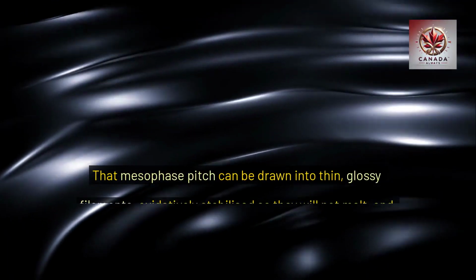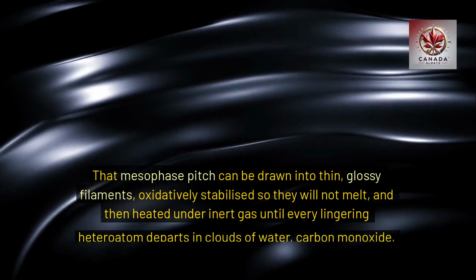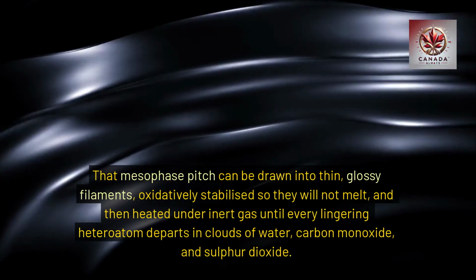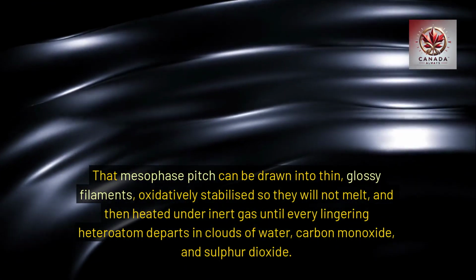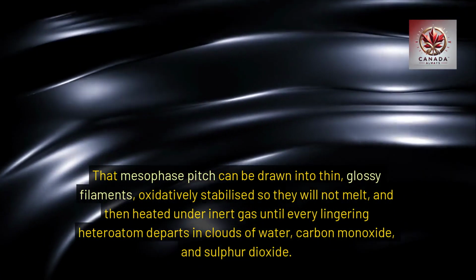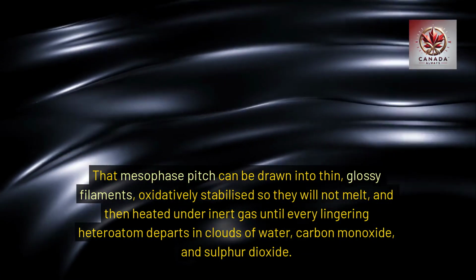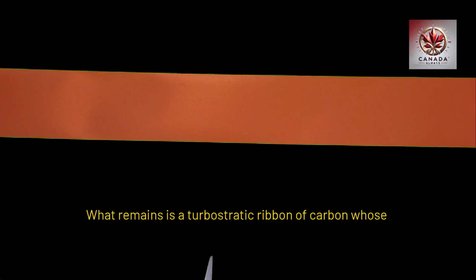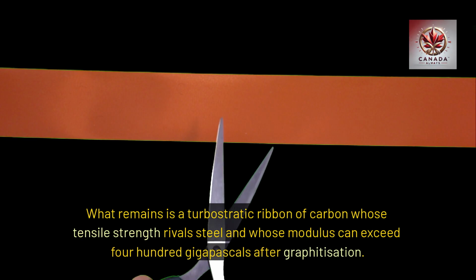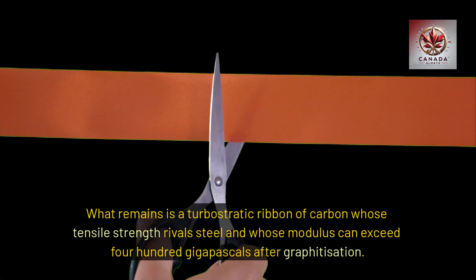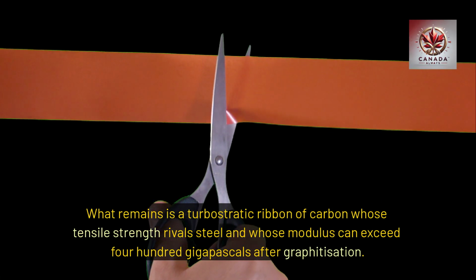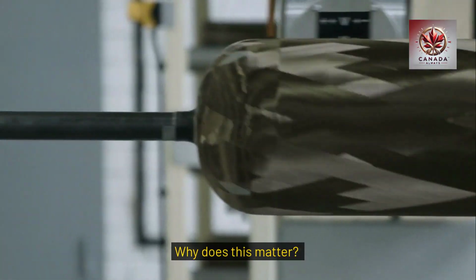That mesophase pitch can be drawn into thin, glossy filaments, oxidatively stabilized so they will not melt, and then heated under inert gas until every lingering heteroatom departs in clouds of water, carbon monoxide, and sulfur dioxide. What remains is a turbostratic ribbon of carbon whose tensile strength rivals steel and whose modulus can exceed 400 gigapascals after graphitization. Why does this matter?